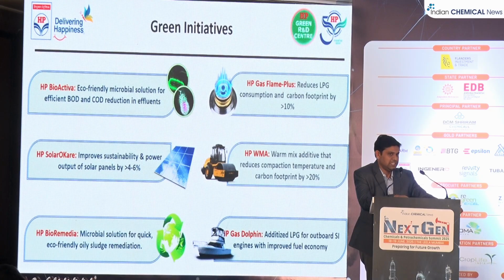If you use HP Bioremedia for bioremediation, we can see within 70 days, 70% of oil will be degraded. And it generally takes 6 months to completely remove the oil from the oily sludge. Then HP SolarOcare is our solar panel cleaning additive. We have seen that by using this additive, as compared to normal soap water, there is a 6 to 7% improvement in the efficiency of power production.